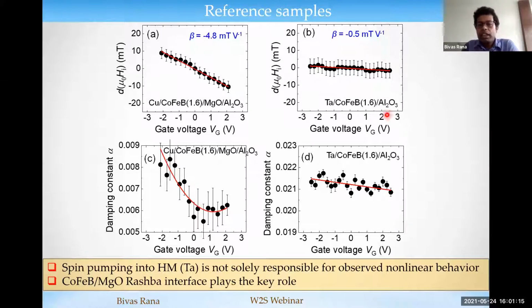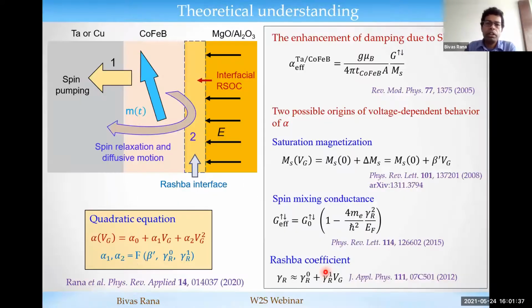Okay, and in the second scenario, we replaced the MgO layer by alumina. But in that case, we didn't see any nonlinear behavior. Then our conclusion is that probably the CoFeB/MgO Rashba interface plays a key role for this nonlinear behavior.